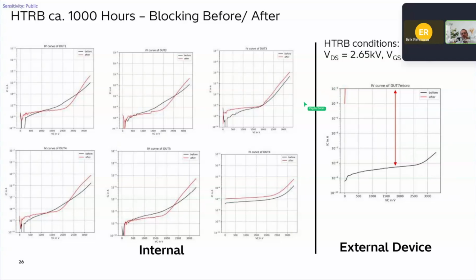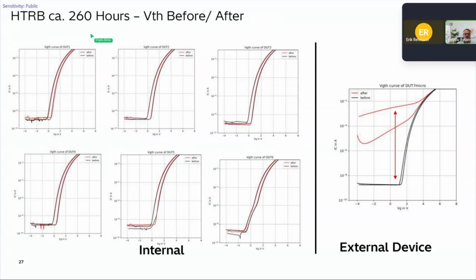Also in terms of reliability, then we test electrically to see what happens. So you see an example of testing HTRB, 1,000 hours, and then the IV curves before and after. We had an external device that we bought under the same conditions, and had a bit of a surprise in difference in leakage current after this 1,000 hours HTRB. So yeah, we spend a lot of care looking at this reliability aspect of silicon carbide. The same for VTH. This is also quite classical in terms of degradation of the gate dielectric or other degradation that happens in the channel with time, and then we try to observe what happens after many hours under voltage.